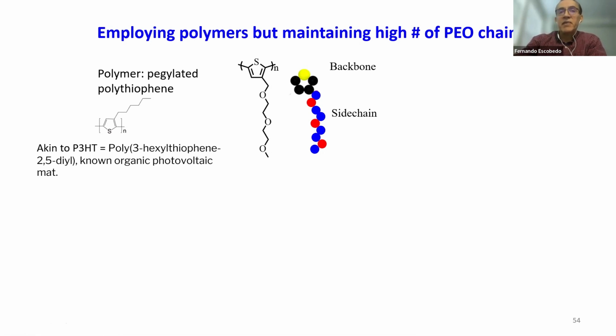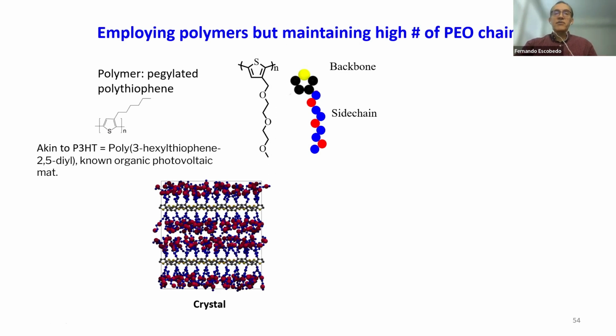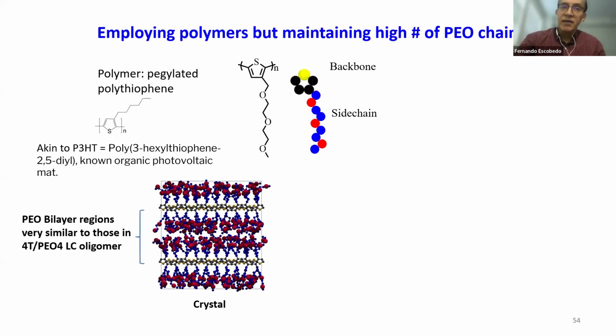Now, this system, just like P3HT, is expected to form this crystalline phase that looks something like this. You see that the thiophene rings will tend to crystallize into these planes, while the side chains will form this bilayer structure. Now, it shouldn't escape your eye that these bilayer regions of PEO are very similar to the layers of PEO that we had in the liquid crystal oligomer that we studied before. So in that sense, many of the lessons will be transferable to the other system as well.